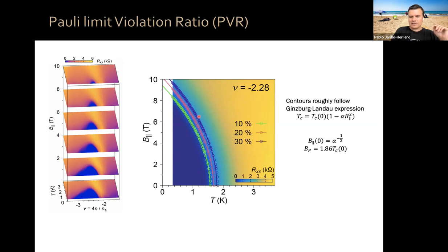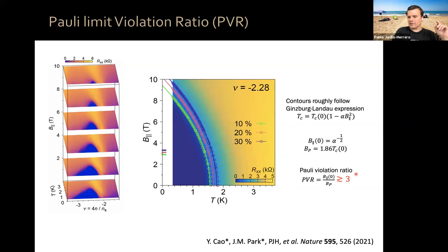We can see that these contours follow a parabolic, Ginzburg-Landau parabolic dispersion. So we can actually extract what the Pauli limits are at zero temperature. And as you can see, superconductivity survives to much, much higher values than the Pauli limit. In fact, the Pauli violation ratio at this particular filling factor is in excess of a factor of 3, okay? Now,